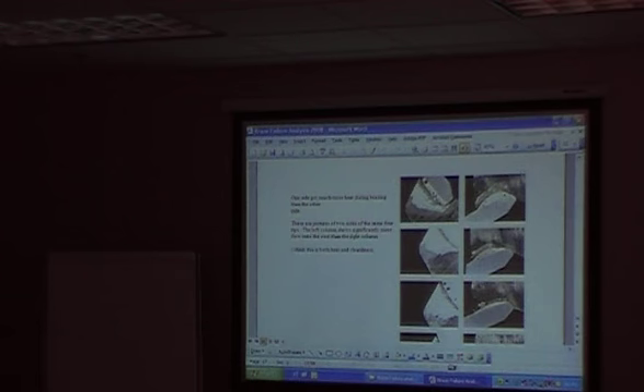If you have a really good brazer and highly skilled, it gets worse. If they're conscientious and highly skilled, you're much more likely to see this. It's a cleanliness problem typically, but they don't know that and they have no way to address cleanliness. So they work with what they do have, which is temperature and pressure. They tend to overheat the braze alloy. They tend to push it in too hard. You can see here, this is much too big a shoulder on it.